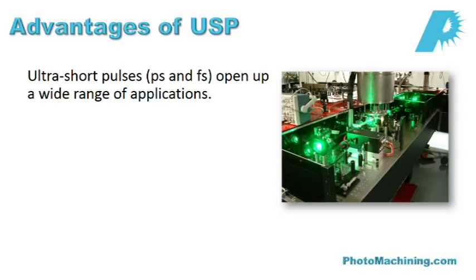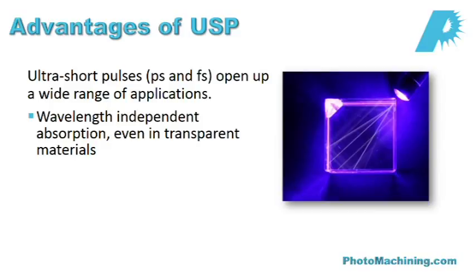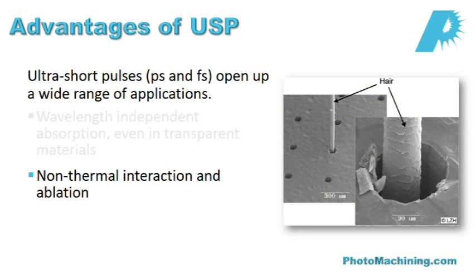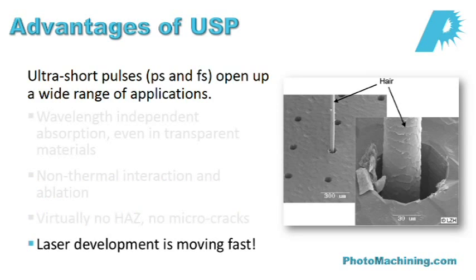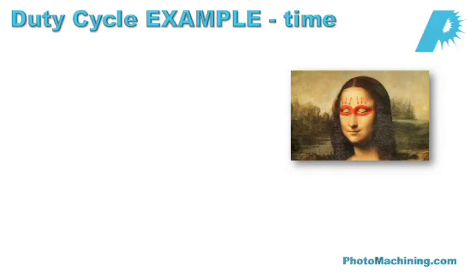With this high peak power intensity, what are the advantages of ultra-short pulse lasers — picosecond and femtosecond? Number one, they open up a whole new range of applications not accessible with other lasers. Number two, with short enough pulse lengths you get predominantly wavelength-independent absorption, even in otherwise transparent materials. For instance, a femtosecond green laser can ablate glass, even though normally green light passes right through glass. It's a basically non-thermal, first-order interaction and ablation — virtually no heat-affected zone and no micro-cracks. This technology is developing and moving quite quickly.